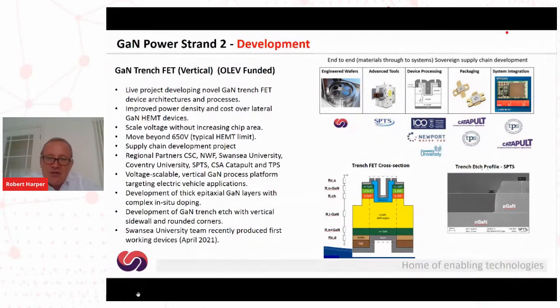In silicon, you can actually dope the different layers using a technique called ion implantation to give you an NPN sort of structure, but that's not possible with gallium nitride. If you try and implant it, all you do is destroy the crystal structure of the material, and you can't recover it by annealing it. So we've had to control the doping of the structure by in situ doping the structure epitaxially. So we've actually had to grow differently doped gallium nitride layers on the surface of this material, and that's been extremely challenging. We're using silicon for the N-type dopant in this case. We're using magnesium for P-type dopant, but P-type dopant in gallium nitride is extremely challenging.